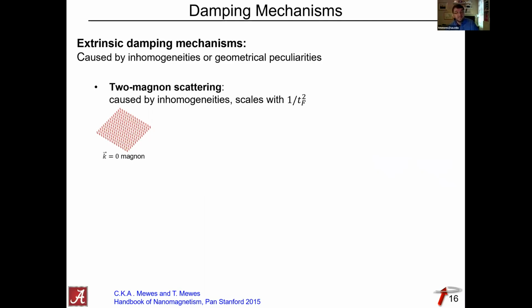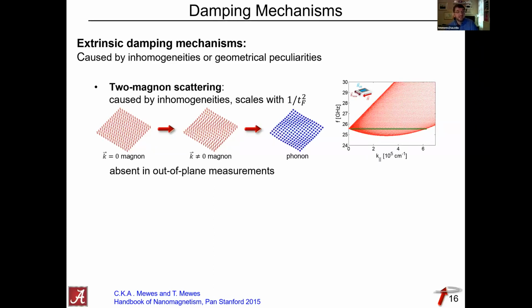typically at interfaces. If it's interfacial in origin, it scales like 1 over the thickness of your film squared. That's a good handle that you have to determine whether two-magnon scattering contributes significantly to your line widths, by just varying the thickness. So how does it work? Well, you have this ferromagnetic resonance, or K = 0 magnon, which then scatters into a propagating magnon. And then eventually this will dissipate to the lattice.